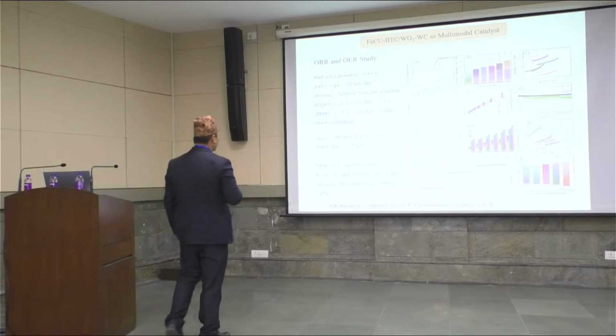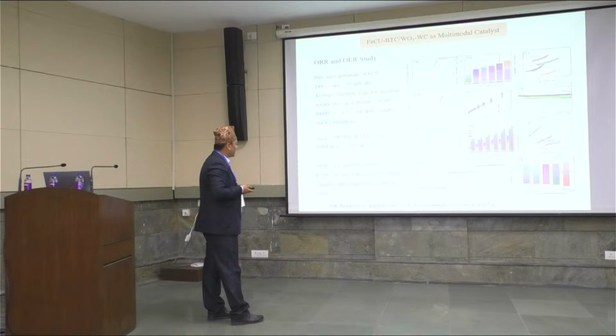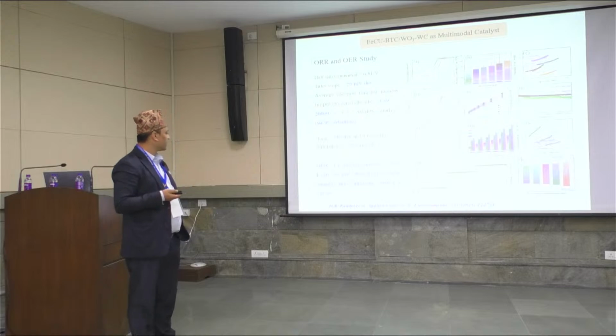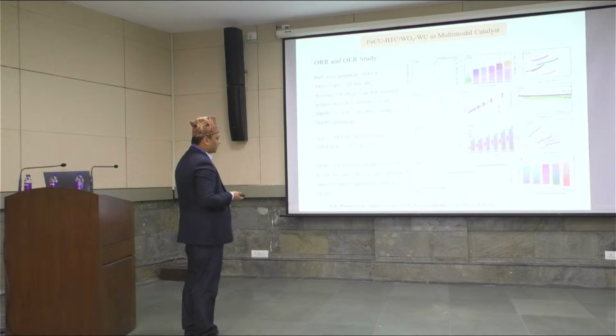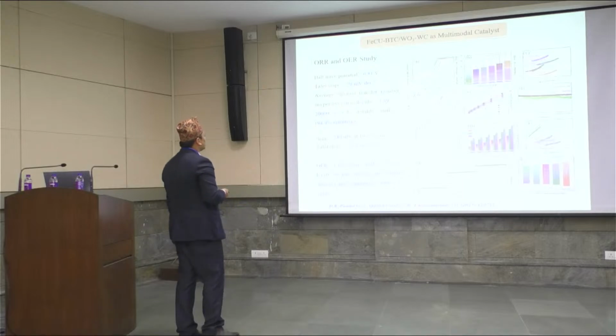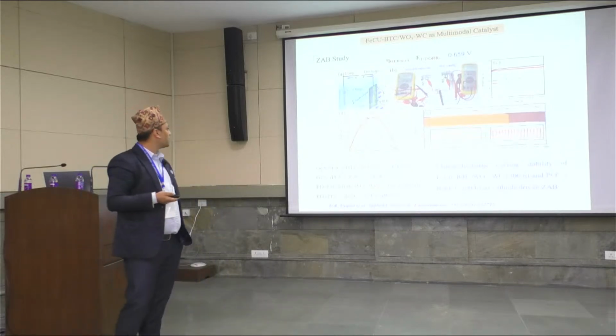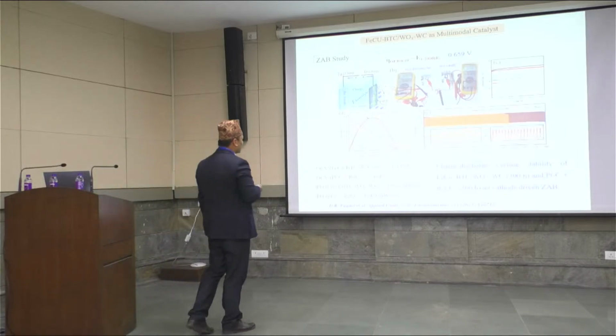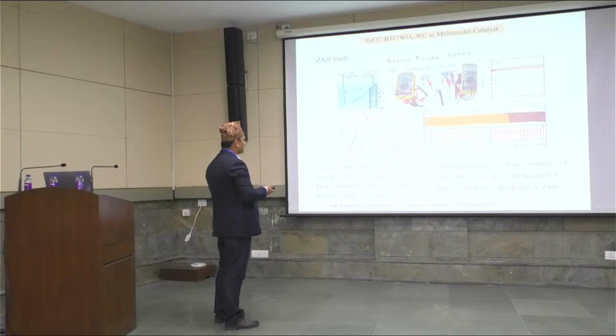And similarly for the OER study, we found a very low overpotential, around 249 millivolt at 10 milliampere per cm square, and the Tafel slope. We also did the stability analysis at different current densities like 10, 50, and 100 milliampere per cm square, and figure J shows good stability. And we did the bifunctional catalytic activity by plotting the OER versus ORR plot. Similarly, if the catalyst shows good OER and ORR activity, we can check for the zinc battery, and the zinc battery property with 0.659 volt potential difference. We checked by different methodology, and it shows an open circuit potential of about 1.435 volt.